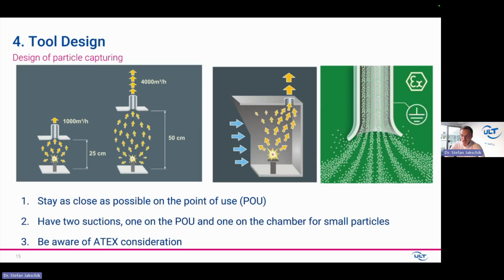And how to make a proper capturing is shown on that slide. First thing is go as close as possible to the source of the particles. If you see on the left side, if you double the distance, capturing efficiency gets worse, and you need four times the volume flow, which in the end is a lot of additional cost. So try to come as close as possible to the surface.